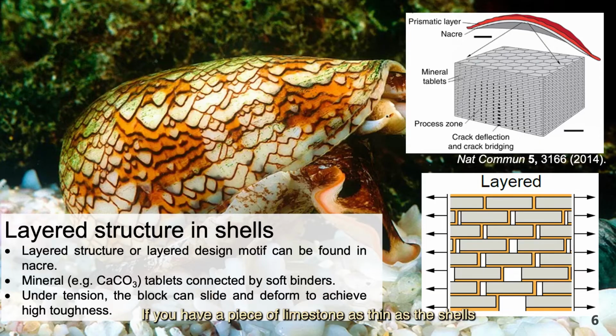If you have a piece of limestone as thin as the shells and you bend it, it will just break immediately. However, the shells are much more flexible and robust. Nacre is about 3,000 times tougher than limestone. While nacre and limestone are mostly calcium carbonate, you may wonder why nacre is much tougher and damage tolerant.